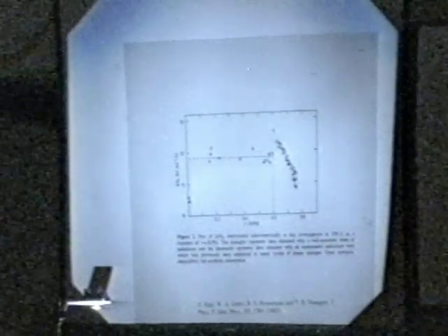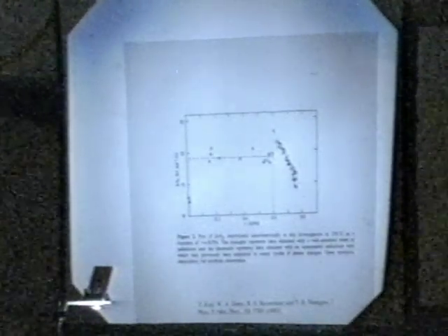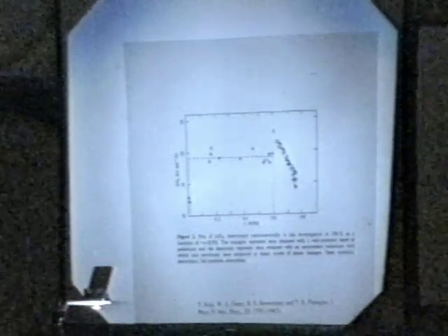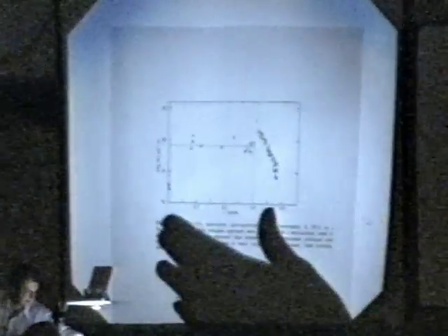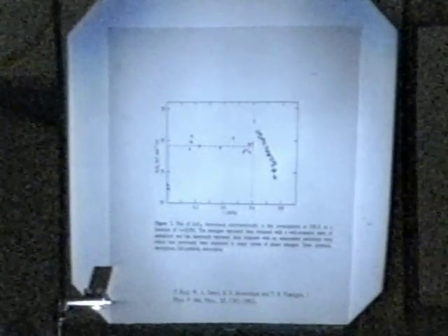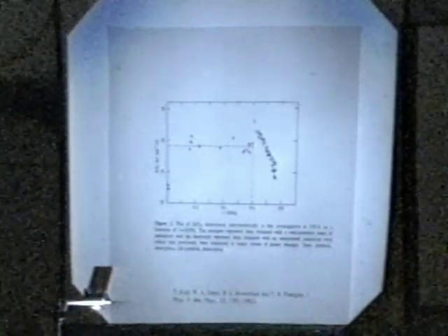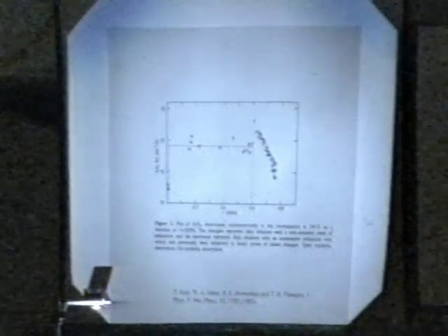Now, you say, well, that's all very well, lots of calculations, let's see some real experimental data. Here are some real experimental data. Again, plotted all as positive numbers because the authors here, these are experimentally determined, calorimetrically determined, are plotting both absorption and desorption on the same plot, so they've ignored the sign. So again, if you want to put in the units that I put in, it's going to look like that. Basically, we see the tendency towards endothermic absorption as we go to high loadings. Again, we're going to meet an intercept of about 0.85 as we saw from the theoretical calculations.